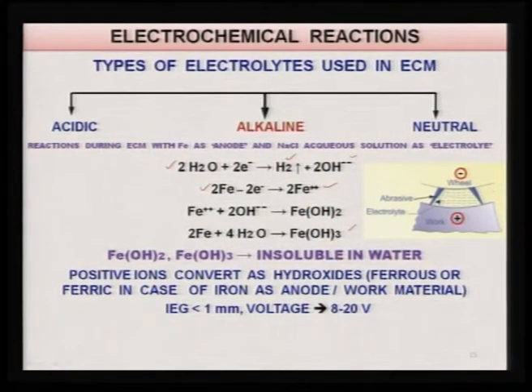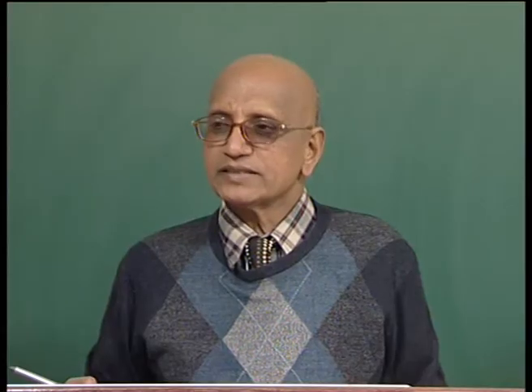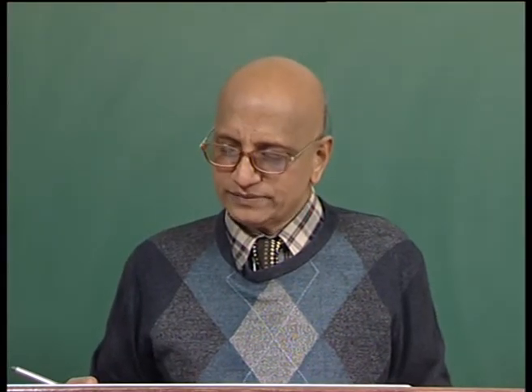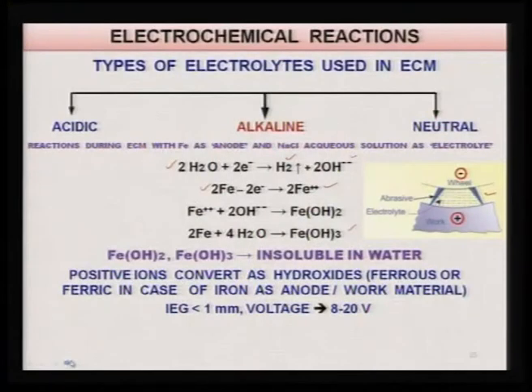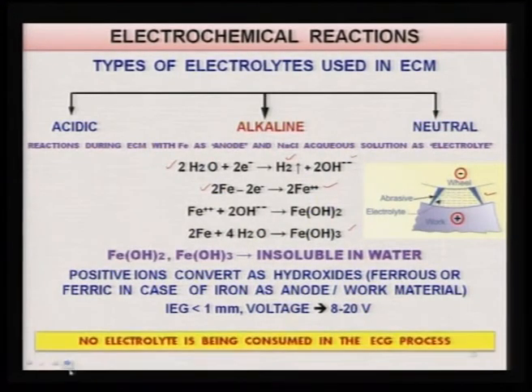Now, in this particular case, as you can see here, inter-electrode gap is quite low and it depends upon what is the projection of the abrasive particle out of the grinding wheel, and normally it is quite less than 1 millimeter. The voltage applied is around in the range of 8 to 20 volts. Now, we can clearly see from these reactions that no electrolyte is being consumed in the electrochemical grinding process, and this was true in case of electrochemical machining.